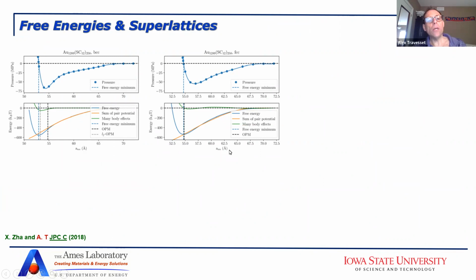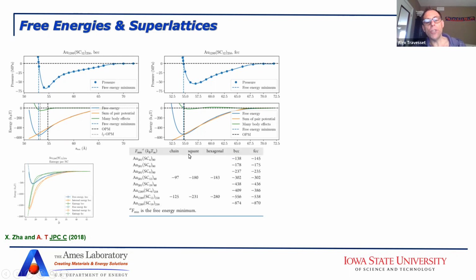The next thing that we looked at is what happens with single component superlattices. So we form BCC and FCC structures. So we compute the pressure, and then by integration of the pressure over the volume, you compute the free energy, and we compare the free energy to the sum of the pair potentials. And you can see here that in general they agree fairly well, because basically here the nanoparticles are behaving as hard spheres, and therefore they are well described as two-body interactions. And there are here a few calculations for chain, square, hexagonal, BCC, FCC. You see that in general, for short chains, you form a FCC structure. For longer chains, it becomes more like BCC, although the precision of the calculation is not, let's say, amazing.